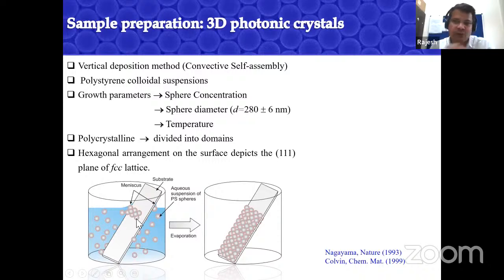And we tried a lot of recipes by trial and error. We optimized the growth. We have this colloid spread in the suspension, and we keep a glass slide. And you keep this in a controlled environment, basically a temperature controlled oven. And after a few days, the water gets drained off, and this forms a self-assembled crystal on a glass substrate. So we don't know much chemistry, but we learned by trial and error, and it works for us. And it's quite repeatable for different diameters and different spectral ranges. So after 4-5 days, you have a very nice crystal on a glass substrate, which you can hold in your hand. Okay, and this was quite popularized in the 90s and 2000 by a couple of papers, and we just learned from this and made it.